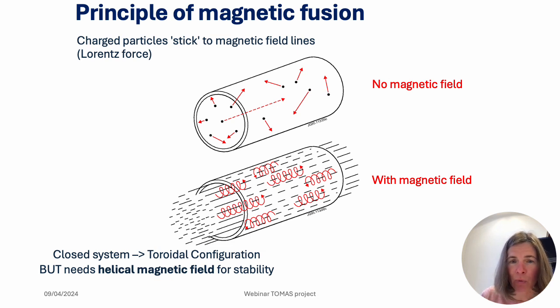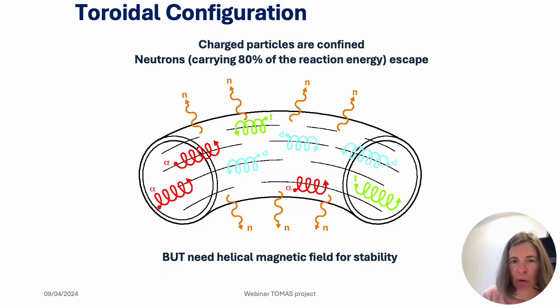A solution is then to bend the cylinder on itself and to make a donut shape, a toroidal configuration. There you just close the ends, and you do not lose the particles anymore. They come back. So the charged particles here, the electrons, deuterium, tritium, and also the helium-4 that is produced, they're all charged particles. They're all nicely confined in your donut. The neutron, that's a different story. The neutron has no charge, so it can escape, but it's also good because it's a way to extract the energy out of your reactor. But the charged particles will stay in the donut.